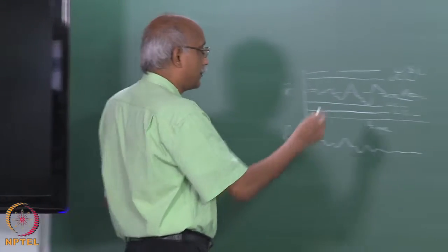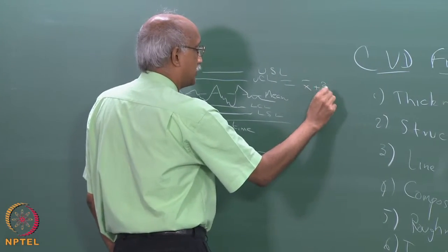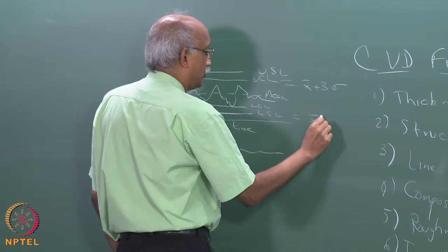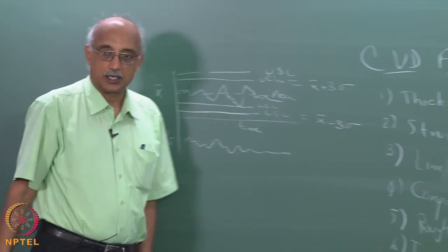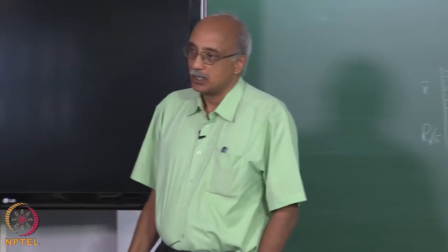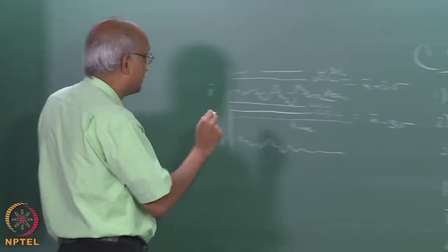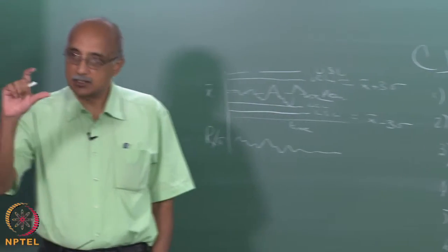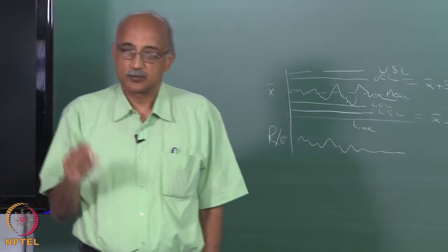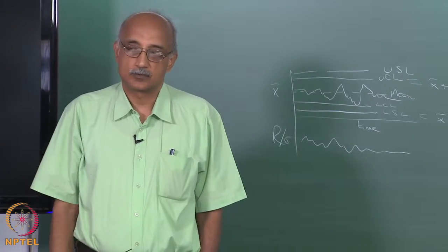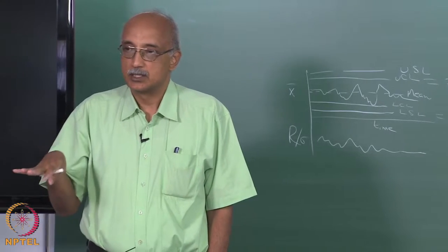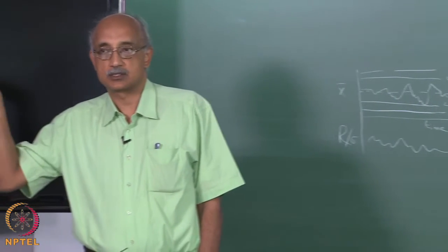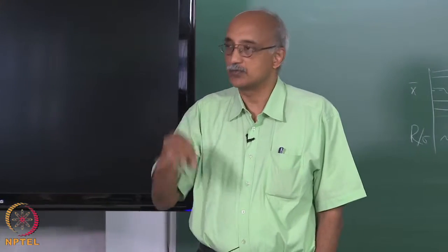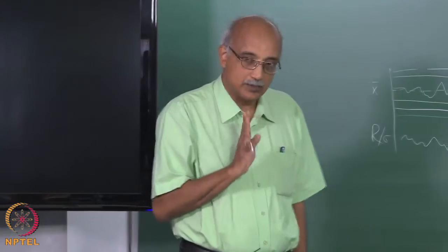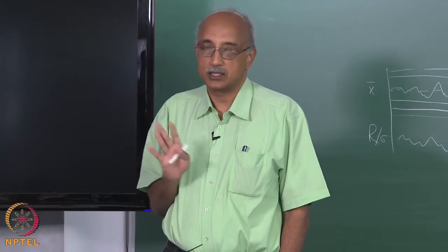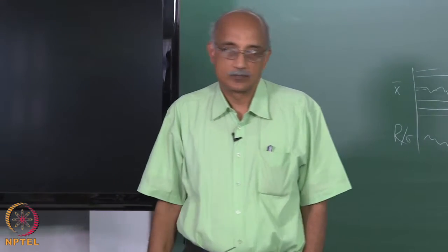So typically, the upper control limit would be set at X bar plus 3 sigma, and the lower control limit will be set at X bar minus 3 sigma. And you would want to maintain your process within the control limits, which should be tighter than the spec limits. So it provides you a safety band. If you can control your process within the control limits, the chances that you will have occasional excursions beyond the specification limit are significantly lowered. So this SPC methodology is absolutely crucial to maintaining quality control over your product.